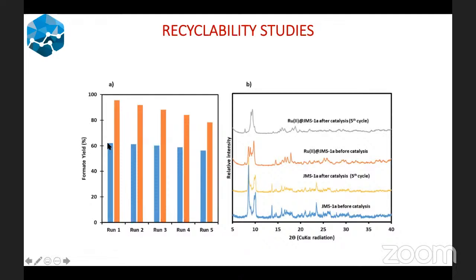And of course, you can see with just the MOF only, you have an activity close to 60%. So that also justifies why we need to include these highly active complexes inside our MOFs. And of course, we checked the PXRD patterns. You can see with the pristine MOF, JMS1, before catalysis and after catalysis, these peaks clearly match, which shows that the structural integrity of the MOF is preserved during catalysis.